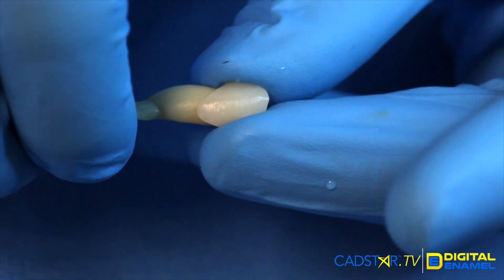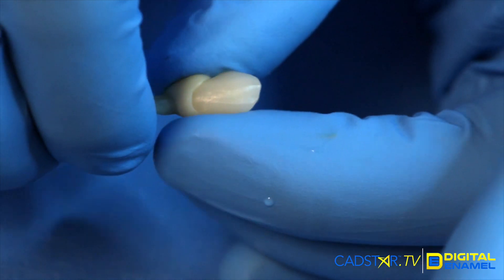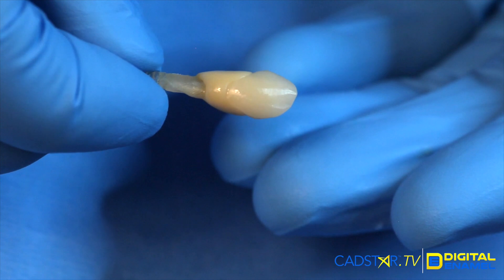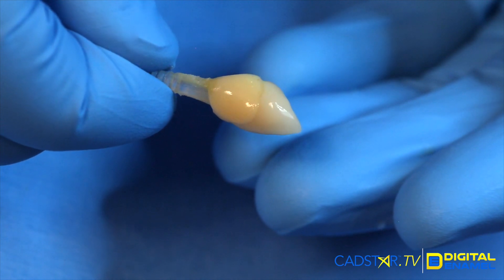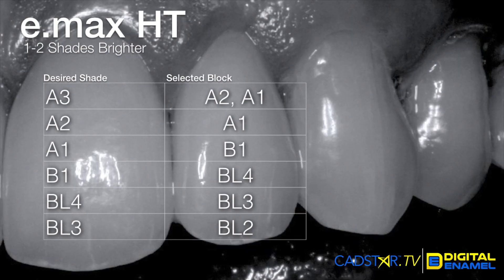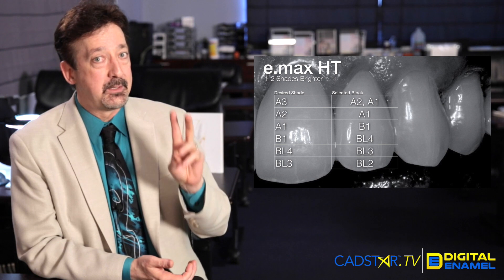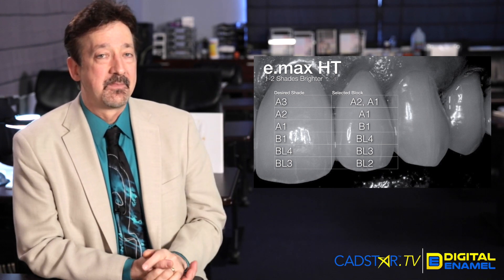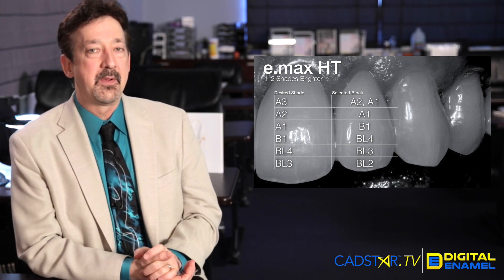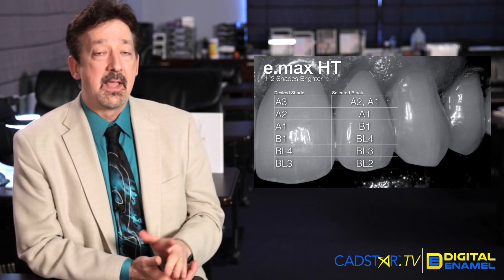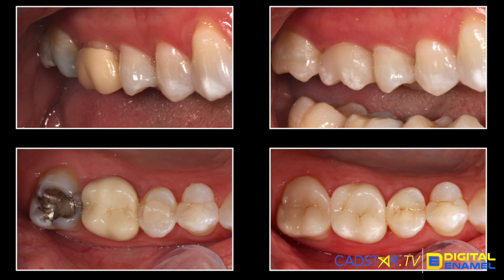Why do I like HT? I love the transparency of the incisal edge. However, they can go gray. Here's how I avoid my HT going gray: number one, I choose one or two shades brighter than my intended shade. If the ceramic is less than 0.7 millimeters, I choose two shades up. If it's thicker than 0.7 millimeters, I choose one shade up, and then I cement it with a warm cement. Particularly for my posterior work, it's clockwork.